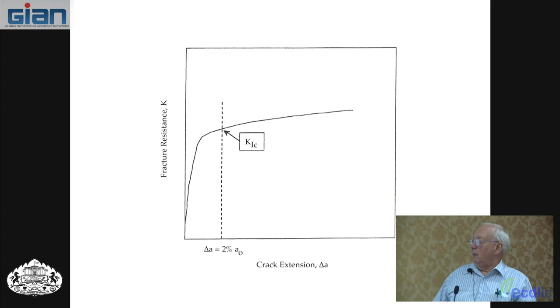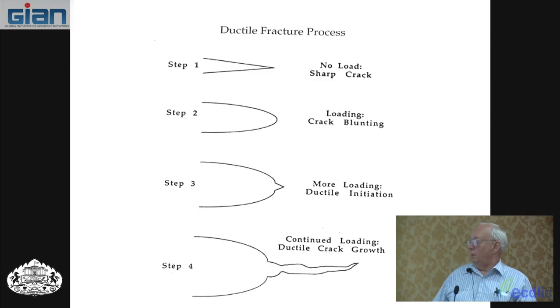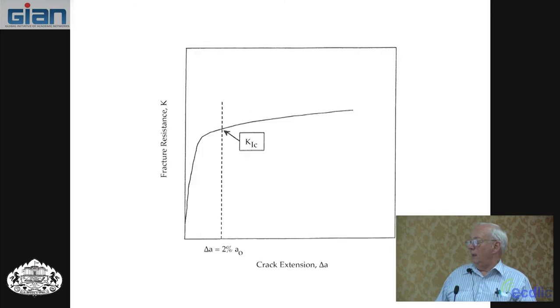So here's an example R-curve. You can ignore this for the time being, but it looks like this. This is crack extension. Delta A would be the current crack length versus the initial crack length. This is essentially this, and that's an R-curve plot. And so you have to be able to pick a point, and in the K1C test, the point you pick is here.